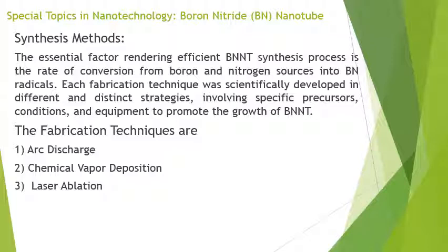Okay, so in this method a target made of boron or boron nitride undergoes a phase transformation from solid to liquid at a high temperature that exceeds the boron melting point, up to 2000 degrees centigrade, due to laser heating. Thus the direct reaction between the surrounding nitrogen atmosphere and the boron target can be enhanced efficiently, resulting in the efficient growth of boron nitride nanotubes.